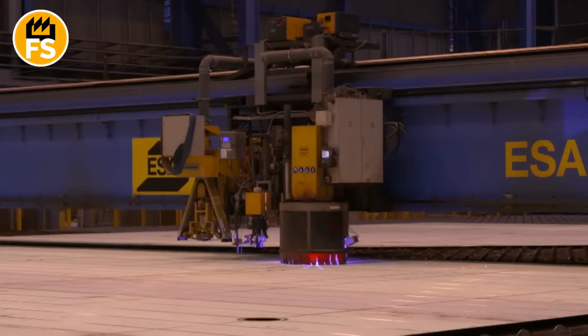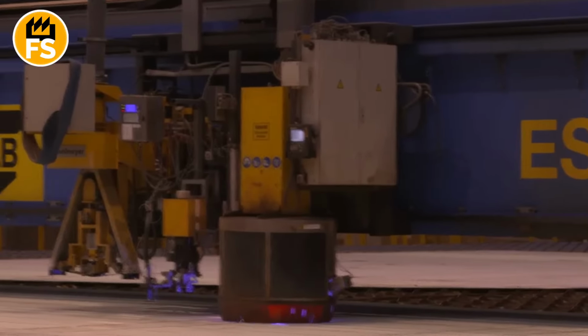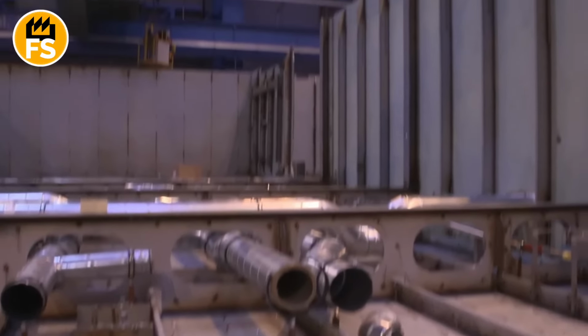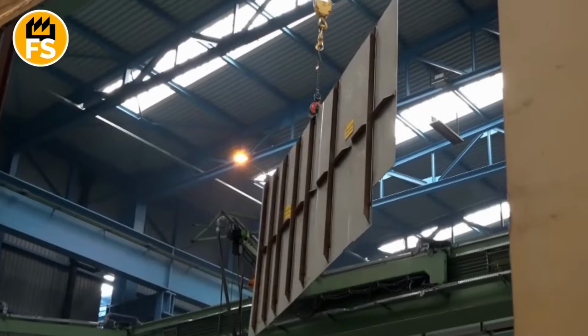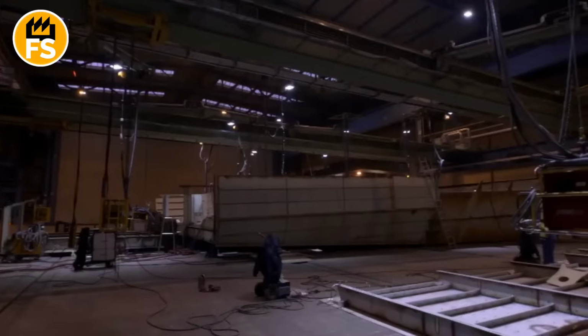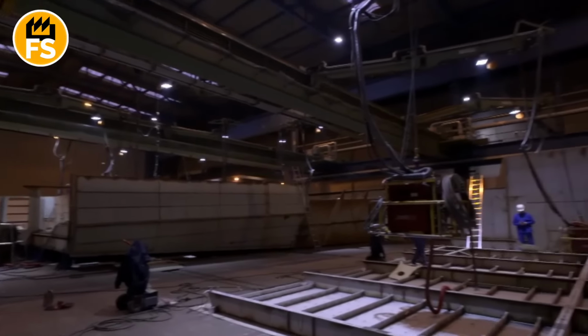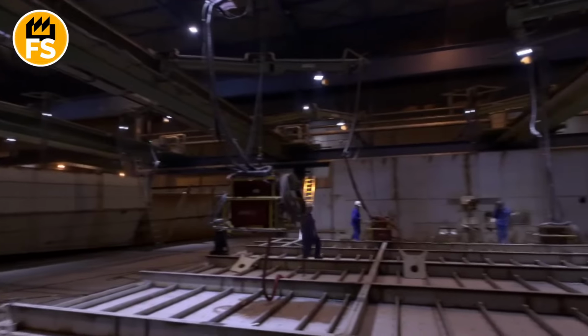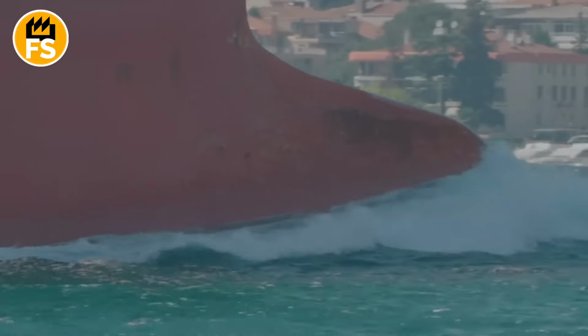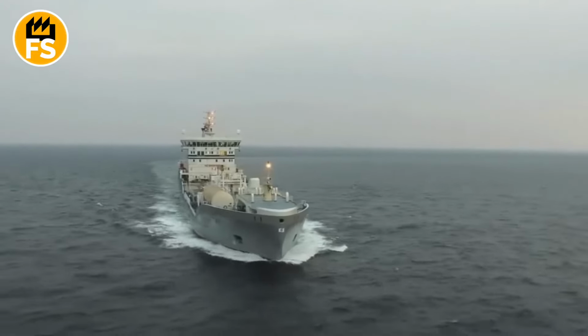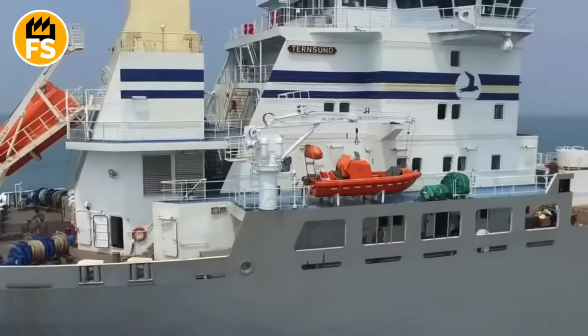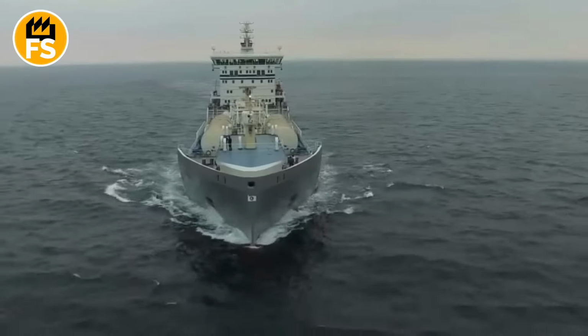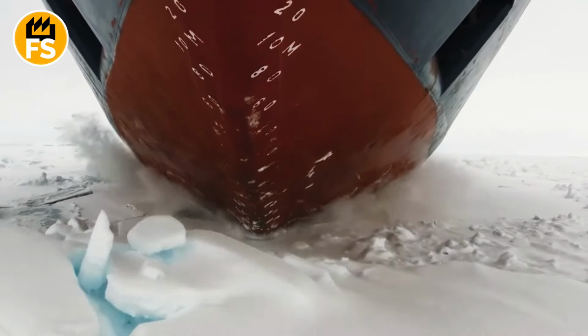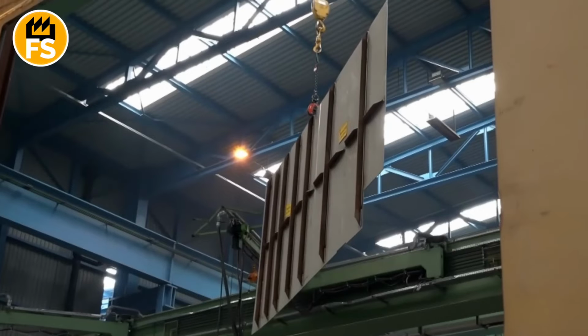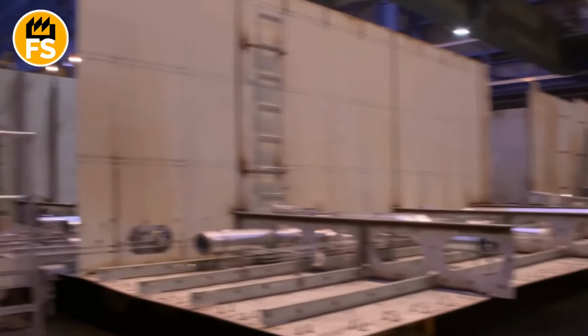Icebreakers are not built whole, like a model ship in a bottle. They are assembled from giant blocks, like a colossal Lego set. In huge workshops, the size of several football fields, the cutting of steel begins. For icebreakers, special low-temperature, high-strength alloys are used. Ordinary steel in the Arctic cold becomes brittle as glass and can crack from a strong impact. But this one retains its ductility and strength even at a temperature of -60 degrees Fahrenheit.